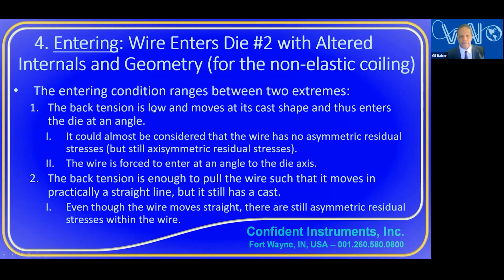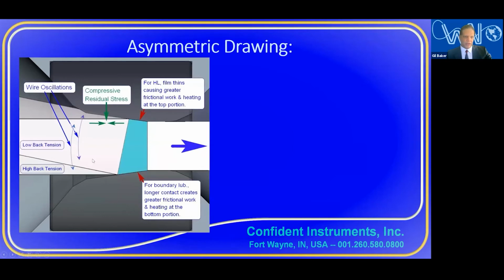The back tension is low. When it's low, it moves at its cast shape and thus enters the die at an angle. So let's see that. I kind of combined this, where you have this wire coming in with a low back tension. So it's coming in with a cast. You would see the cast because the back tension is so low. You'd see the cast between the capstan and the die. And it's coming in at an angle.